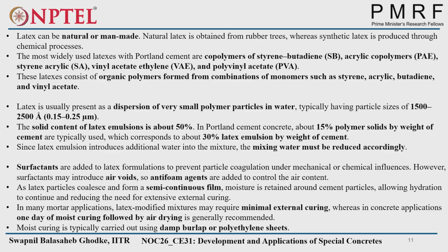But along with that, we have to consider the surfactants. Why do we have to add surfactants? When we add those small polymer particles, there is a possibility that the polymers will come closer and coagulation will happen. To avoid that and get proper dispersion, we have to use surfactants. But there is a disadvantage to using surfactants: there is a possibility of a higher amount of air voids. To avoid the higher amount of air voids, we can use anti-foam agents. So these are connected to each other.